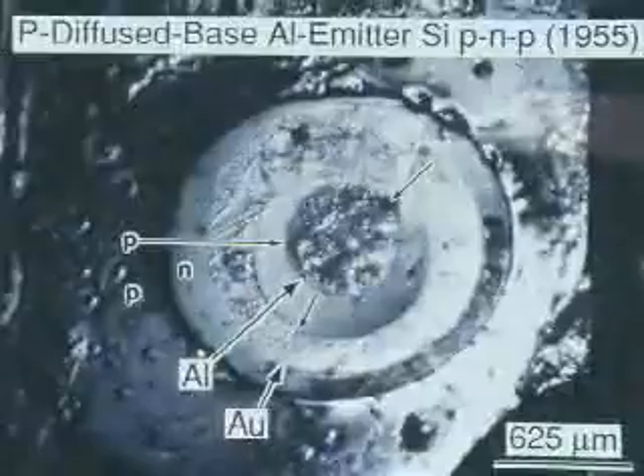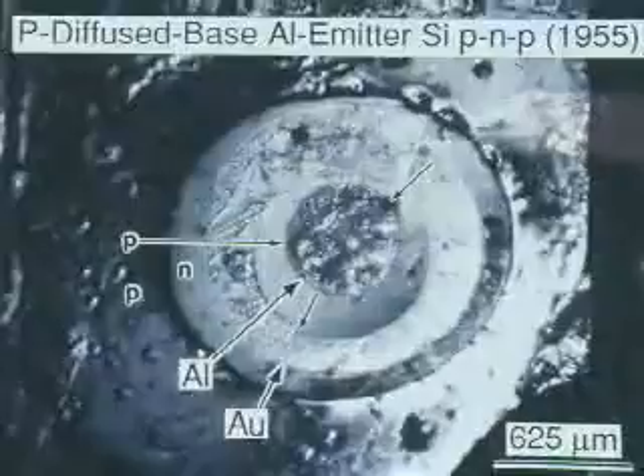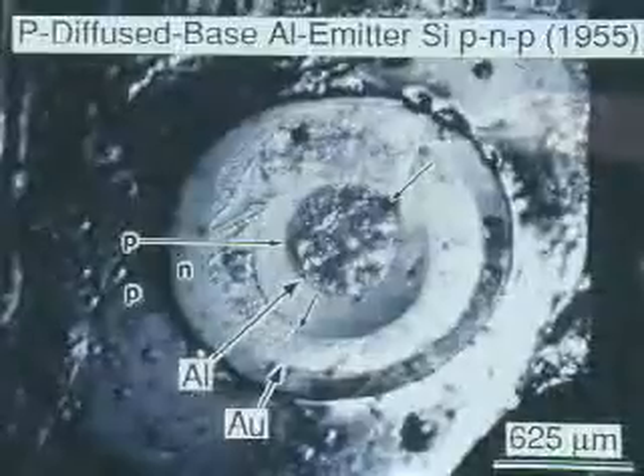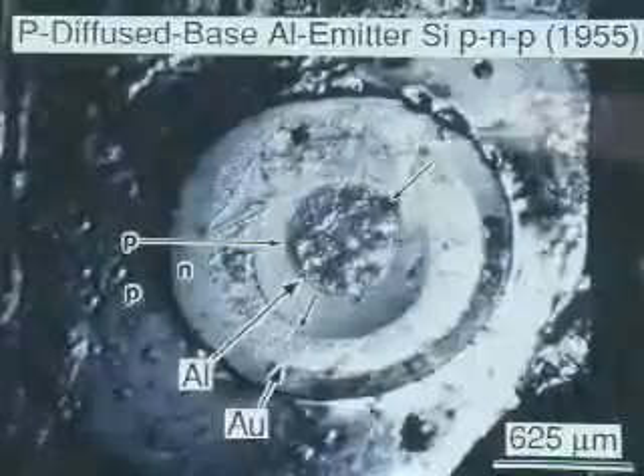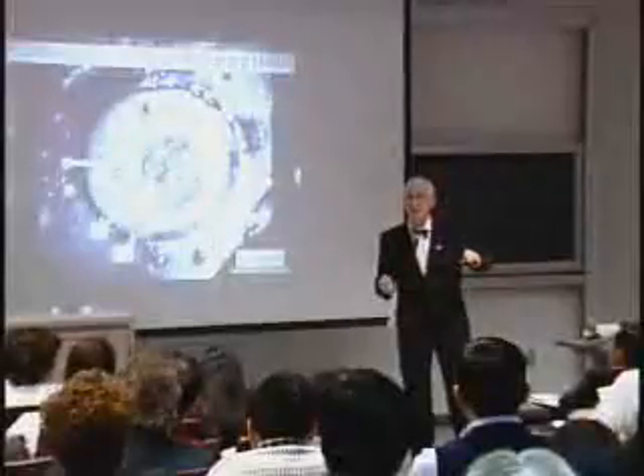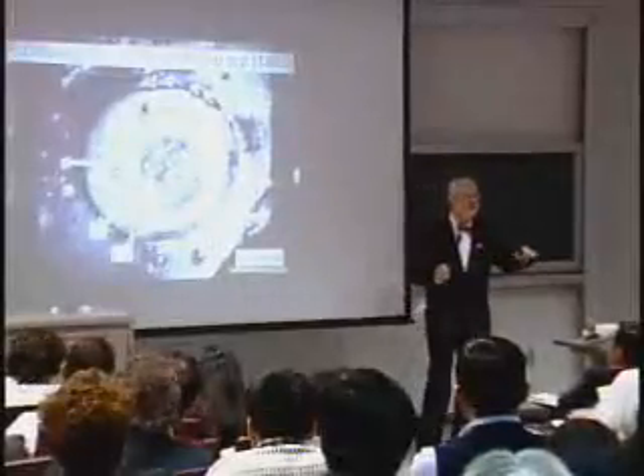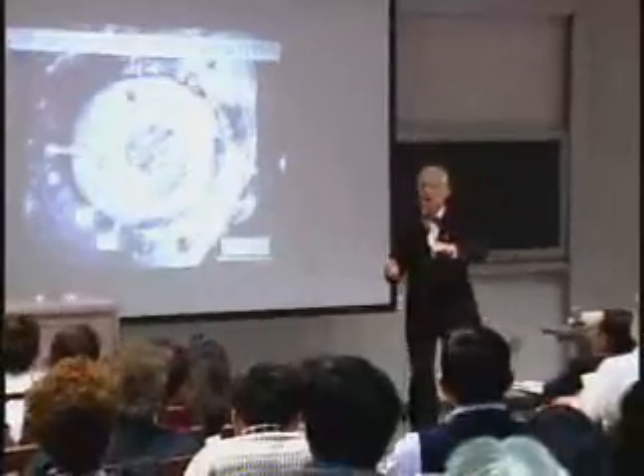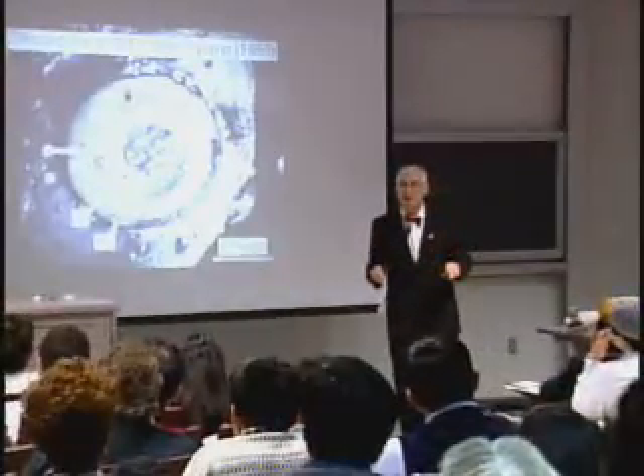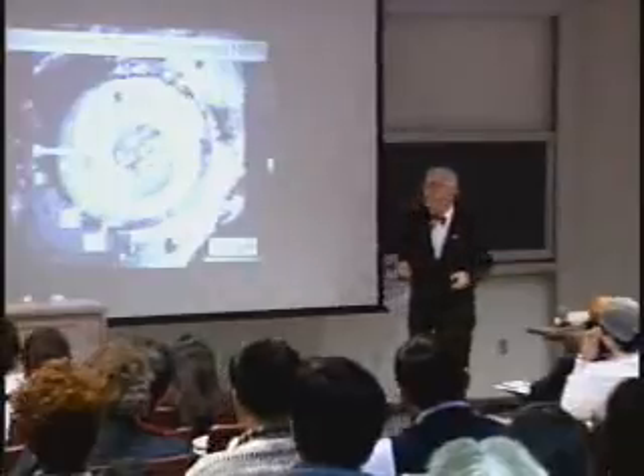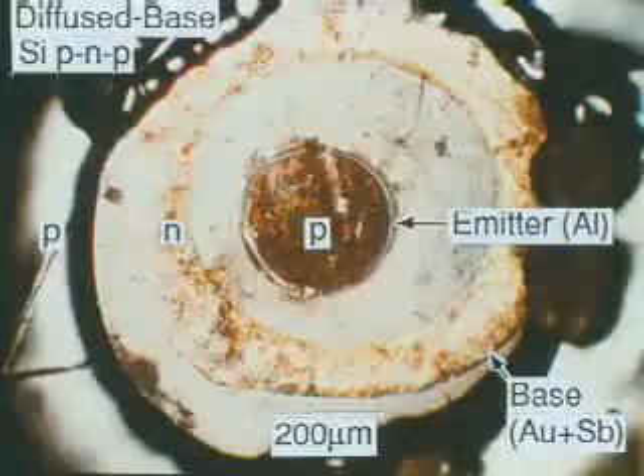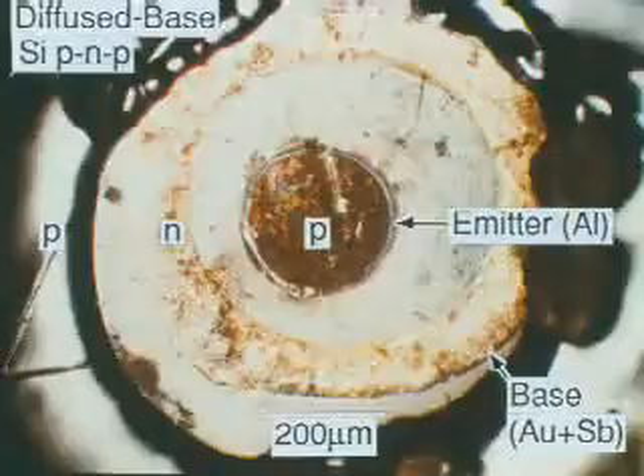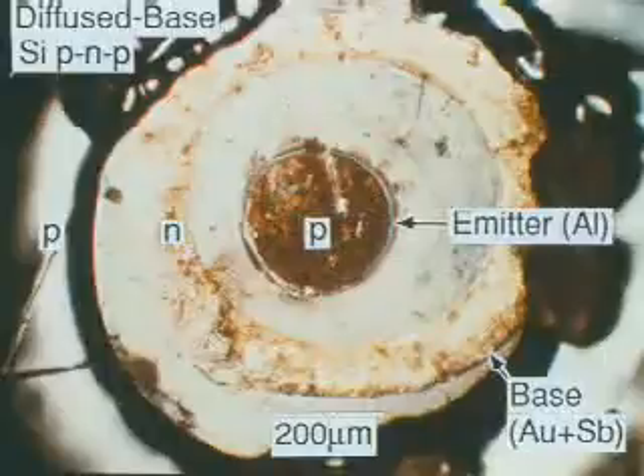We made ring-based structures. They're crude because, incidentally, in another room not far from the evaporator I showed you, there were two people working on the Kodak photoresist process to lay out patterns. But that wasn't far enough along that any one of us would have delayed our work to introduce that into the processing that we were doing on silicon. You see, but the right ideas are being worked on. And here's another view, probably a different one, but the color shows you the aluminum evaporation here, the gold for the diffused layer, and the P underneath.